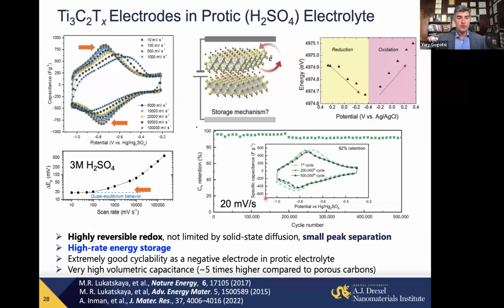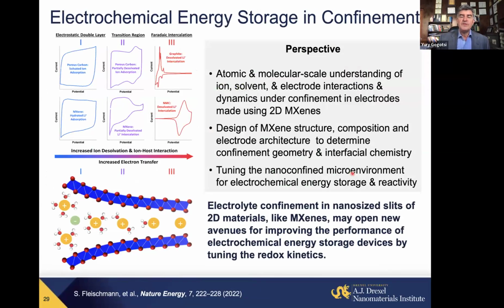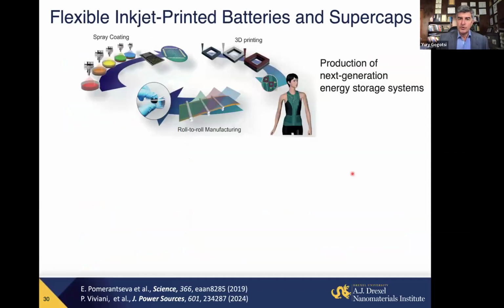And indeed, we showed in aqueous system, we can have charging at 100 volts per second, a 10 millisecond redox charging process. And a supercapacitor made of MXene, we can run for 500,000 cycles with 92% retention of capacitance. And it's still, as you see, there is a redox process, not just double layer that we can see here only. So these materials open new opportunities in energy storage.